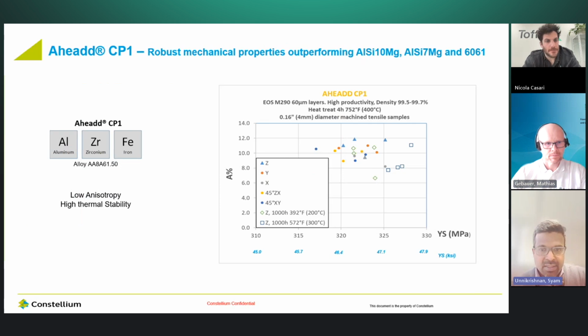Next slide, please. So one of the challenges people find when they print aluminum silicon is the anisotropy. Here in Aheadd CP1, when you print the components in most of the directions, X, Y, Z, or 45-degree angles in different planes, we see only a few MPa difference in all directions. This is a good promise for design engineers to give freedom to design components without restrictions coming from the material.